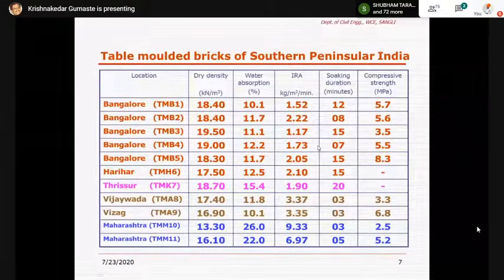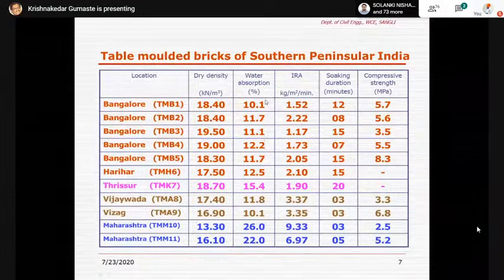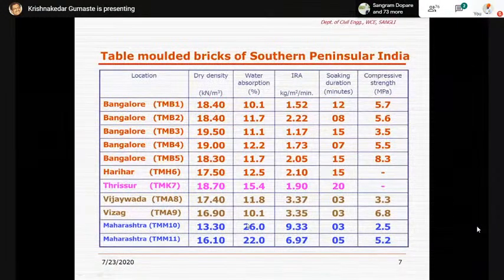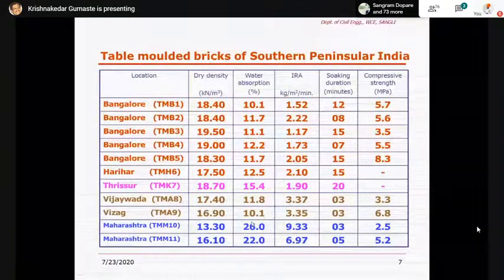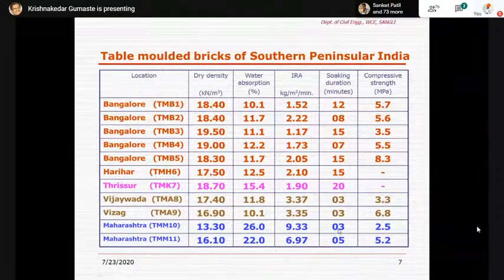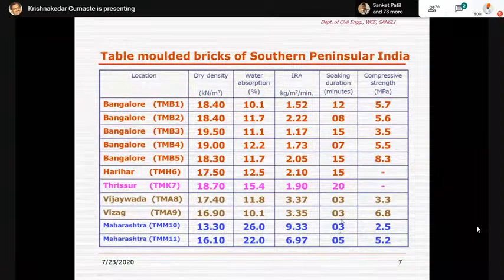So in this table you can see a brick which has a water absorption of somewhere less than 20 requires a soaking duration of 10 to 15 minutes. On the contrary, if the water absorption is very, very large, more than 20%, in that case, the soaking duration is very small, like 3 to 5 minutes. And soaking more than 10 or 15 minutes may saturate the brick in such conditions, and thereby may adversely affect the masonry strength itself.